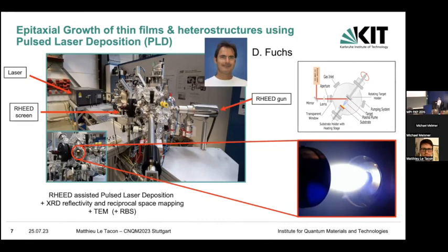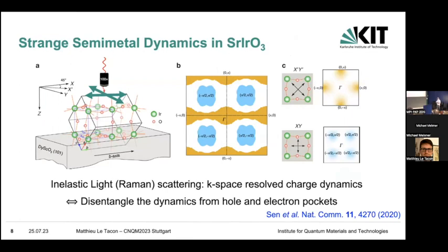And as I'm going to show you, we also do electron microscopy on them. And especially when we start doing new growth, Rutherford backscattering to actually ensure the stoichiometry and the composition of the compound. The oxygen composition, for instance, is very important. So I'm not going to show all the details of the growth and the characterization, but once we grow those materials, we thought we could investigate the charge dynamics with them.